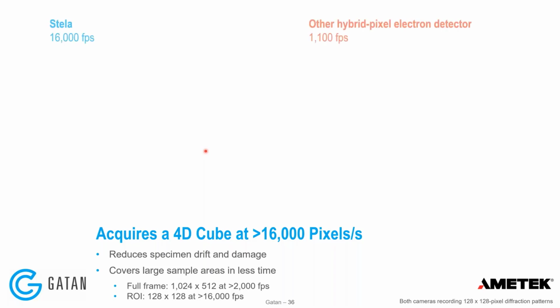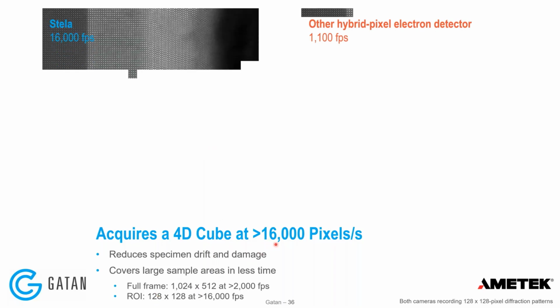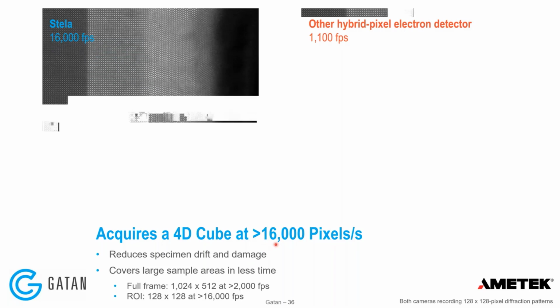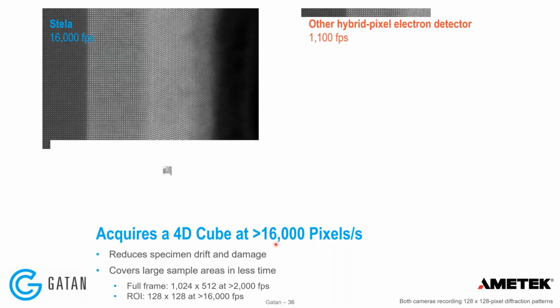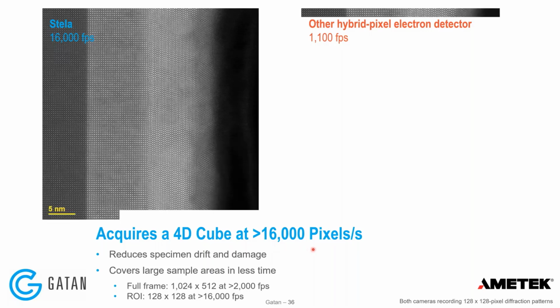So with the Stela camera, you can run the camera at more than 16,000 frames per second. And what that means is that you can run your 4D STEM experiment at more than 16,000 pixels per second. So this is 16,000 STEM pixels, so 16,000 scanning probe positions per second. And what this gives you is that, as I was mentioning earlier, you can collect a larger field of view on your sample in a shorter amount of time. And also, if you have issues with specimen drift or specimen damage, because you're collecting data faster, you can eliminate those problems or at least minimize them.